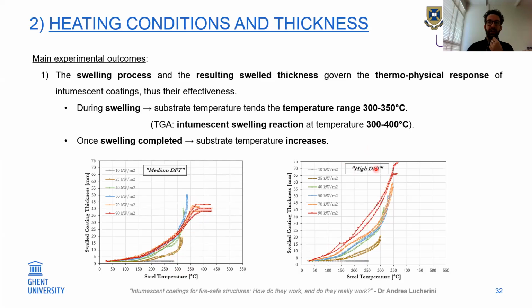In the case of high DFT, you can see that the coating keeps swelling during the whole duration of the test and never, only in a few cases, stops swelling and increases above 350 degrees. So mainly, during swelling, the substrate temperature tends to the temperature range 300-350. And this is, if you remember from the TGA experiments, I showed you that the intumescent swelling reaction happens at temperatures between 300 and 400.